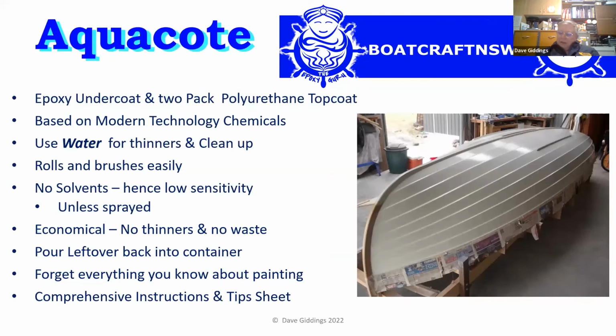Aquacote is the most undersold, under-respected product in the range, and it's what got me on board with all of these products. There's an epoxy undercoat, and it sets as tough as nails, and a two-pack polyurethane top coat. You put that combination over gel coat, and it gives you very good protection for a long time.